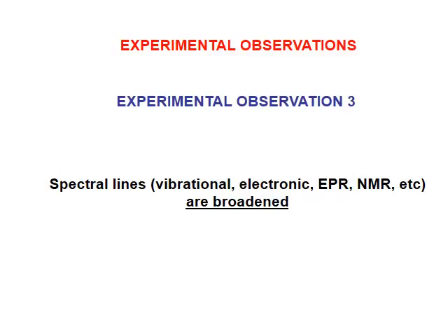This is the so-called inhomogeneous broadening of spectral lines: vibrational spectroscopy, infrared absorption or Raman scattering, electronic spectroscopy, electron paramagnetic resonance, EPR, nuclear magnetic resonance, NMR. All these techniques are sensitive to bond distances and angles, and for that, we will always observe broadening of spectral lines with respect to crystals.